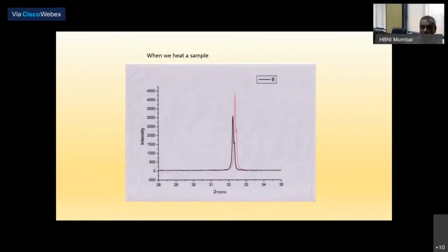Depending on that bonding and the strength of the bond, this average displacement is not the same in all possible directions, as I showed you in my calculation, but it is anisotropic, and the more apt term will be thermal ellipsoid, and we can map this thermal ellipsoid using Bragg diffraction.